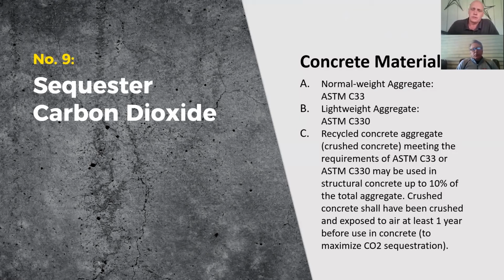In the specification, I would say, consider permitting the use of recycled aggregates made of demolished concrete on a project, and possibly require those recycled aggregates be exposed to air for 1 year before being used. Now, this idea works probably best when you're revitalizing a site, maybe taking existing structures, demolishing them. You can take some of that aggregate, let it stand for a while before the construction starts, and then use it as part of the project. And the reason why that works so well is that carbonation happens accelerated when you have a high surface area to volume ratio. So crushed concrete, high surface area to volume ratio, you can get carbonation happening at a relatively high rate.